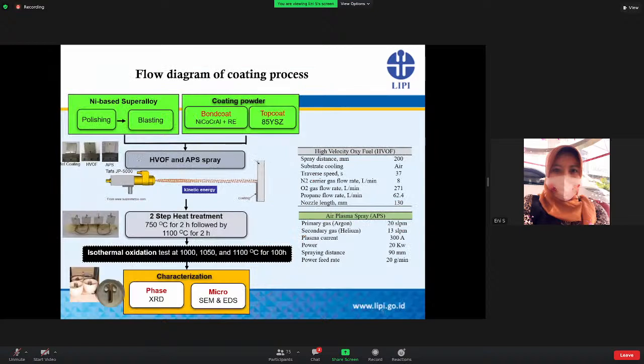So this figure shows the flow diagram of the coating process. Nickel superalloy was polished to 1000 grit and then blasted in order to enable adhesion. Initially, the bond coat material was deposited by using the high velocity oxy-fuel technique, followed by the deposition of the ceramic yttria-stabilized zirconia.